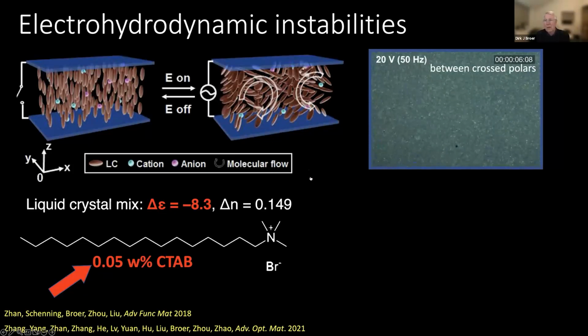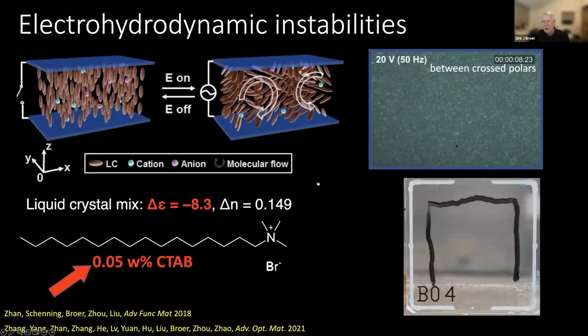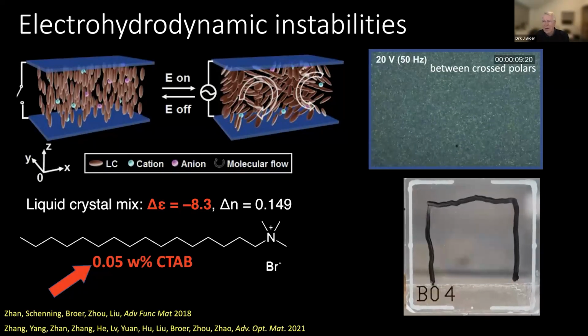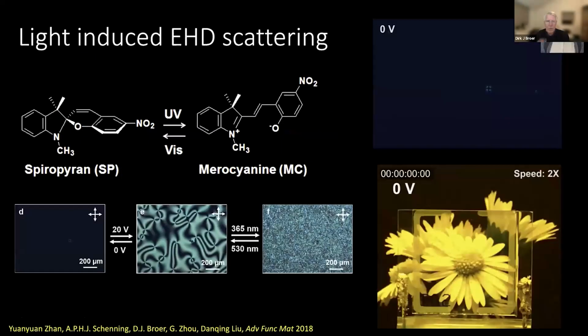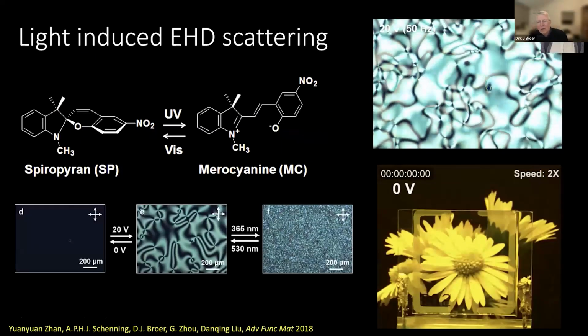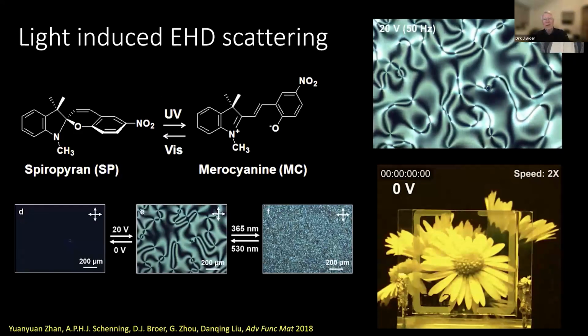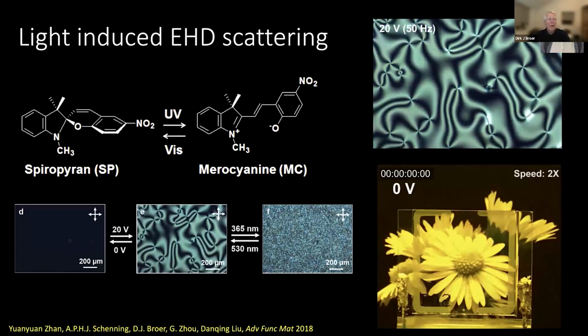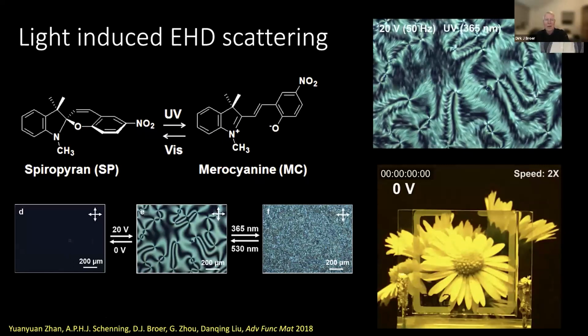But when you bring this in an alternating field, and you start, for instance, with a liquid crystal which is oriented with the long axis of all the molecules more or less perpendicular to the surface, then you bring the system into an electrohydrodynamic oscillation, which changes the system from transparent to highly scattering, as can be seen here. And this, for instance, can be used to make a little smart window, which can be switched from transparent when the surfactant molecules, the ions, are not in an electrical field. But as soon as you switch a field on, you see the scattering of these materials.